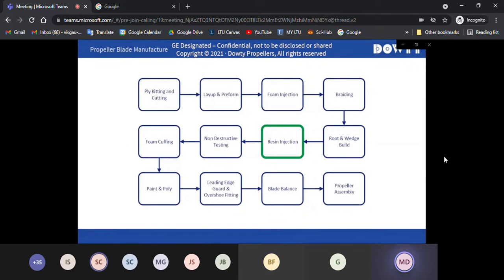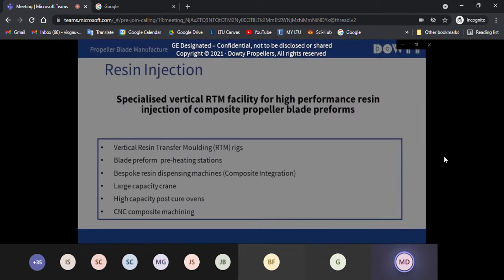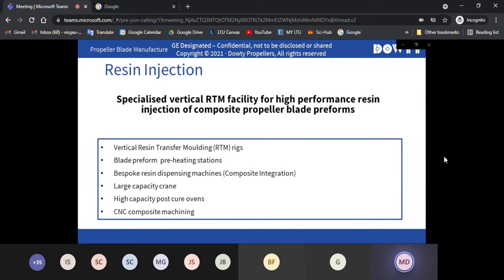At this point, we transition across to the resin transfer molding, or RTM cell, where we put our blade preform, which consists of a foam core surrounded by dry carbon and glass materials, into a mold and inject it with resin under temperature and pressure, where the resin is cured and solidified to form the final composite blade.